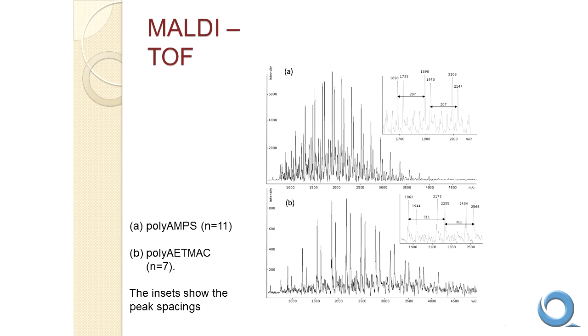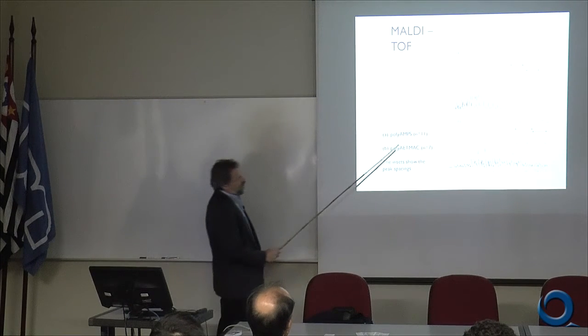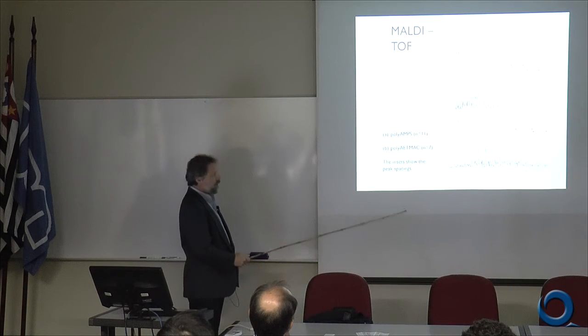All right, this is just showing that we do have the capability to stop the polymerization after that first step. This is an anionic hydrophilic polymer, and this is a cationic hydrophilic polymer that we've polymerized by the RAFT polymerization. They're analyzed by MALDI-TOF mass spectrometry, and what you see is we get an envelope of polymers of different chain length, and we can calculate what the average chain length is. So in this case it was 11, in this case it's 7. And you can see that there's some dispersity in this, that it's not just one polymer with a degree of polymerization of 7, but it's 7 plus or minus 2 or 3, something like that.